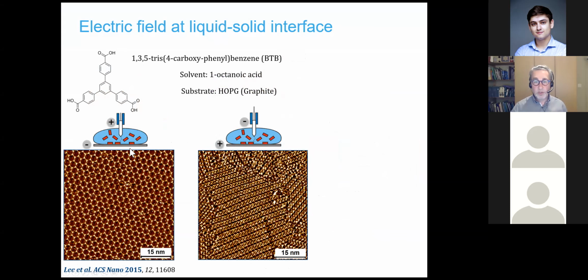Well, first of all, you have the size of the electric field, but you have also the polarity of the electric field. You can bias your tip positive, or you can bias your tip negative. So if you bias your tip positive, electrons tunnel from the substrate towards the tip. If you bias your tip negative, electrons tunnel from the tip towards the substrate. Now for this system here, that has an impact.